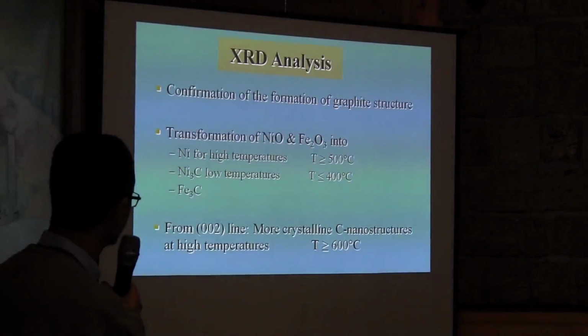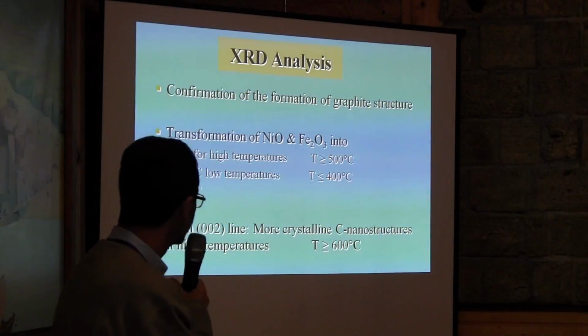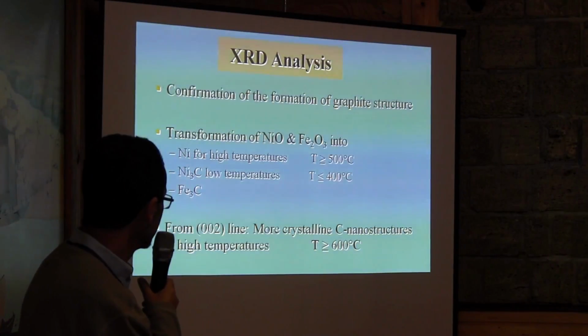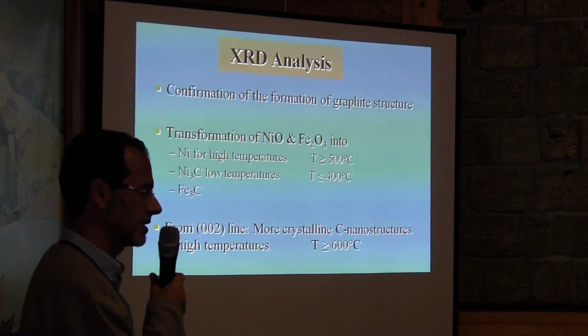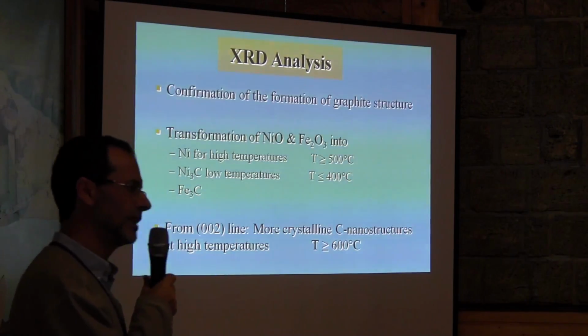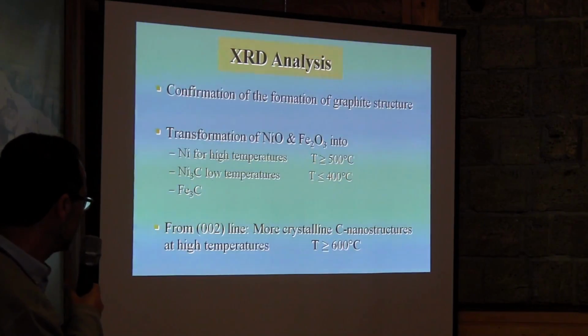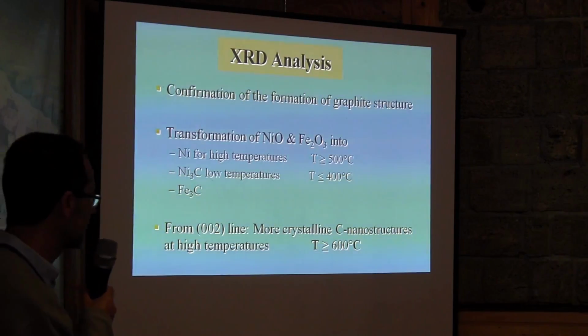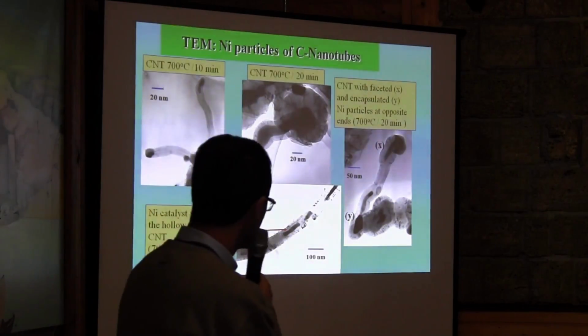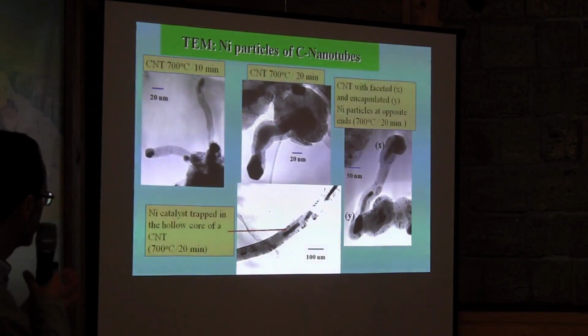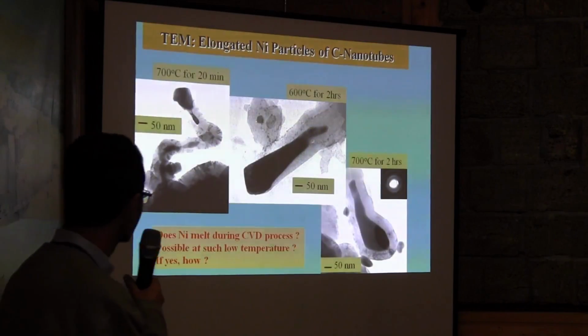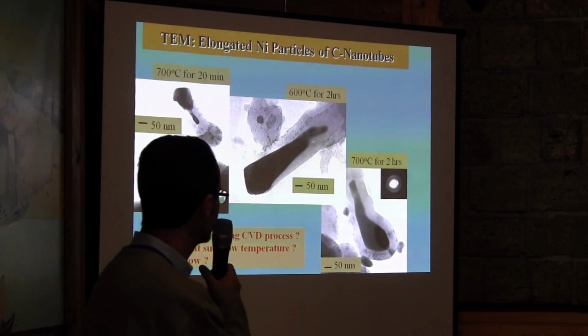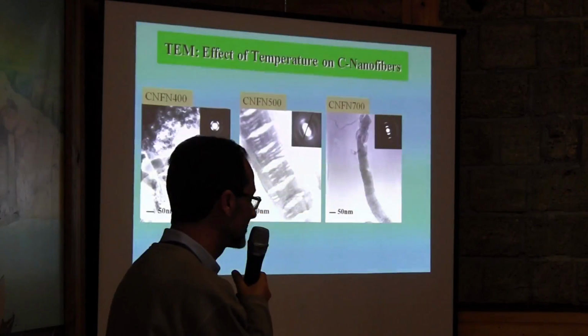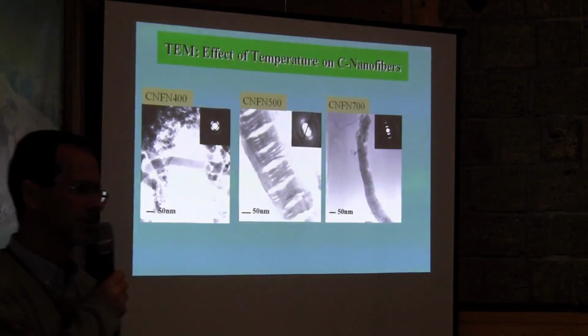Okay, next one please. So this is what we obtained from X-ray diffraction. We obtained nickel around 500, nickel carbide at lower temperature. Imagine, 400 Celsius, you form nickel carbide. And we have high crystallinity above 600. Next one please. So we did TEM, and we can notice different approaches. Next one. Again, I can show you later if you are interested. Next one, please. Yes, this is what I am interested in.